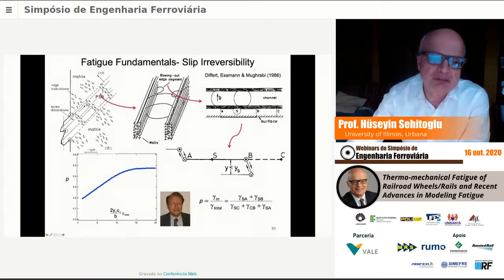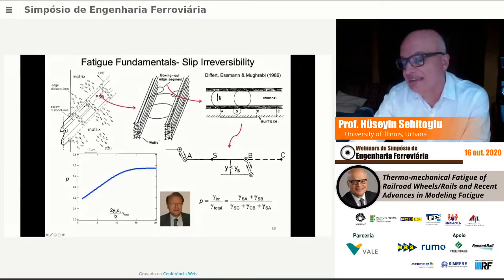We mentioned that fatigue starts from persistent slip bands. That's well known. It's observed, and it's a result of irreversibility. So, if we have a dislocation source here, S, if the dislocation is emitted, it goes to C, and then on the way back, if it reacts to the dislocation of the opposite sign, it's annihilated. So this path, S, C, on the way back, you go to B, and it's annihilated there, but it doesn't go back to S. And same here, from the source S, I go to A, the dislocation moves this way, and it reacts to the dislocation of opposite sign here, it gets annihilated, and so it doesn't return.